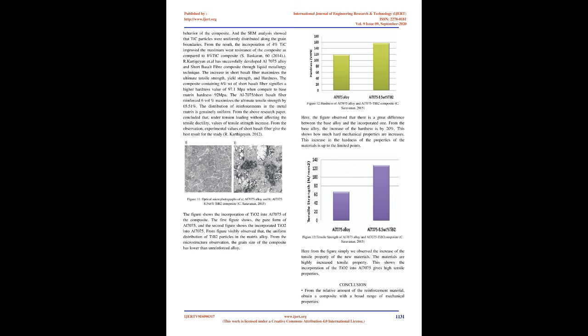Pradeep, 2014. Keshavamurthy et al. studied Al7075 TiB2, processed by stir casting technique using Al 10% Ti and Al 3% B master alloys. Matrix alloy and composite were subjected to microstructure analysis, micro-hardness test, grain size studies, and tensile test. Micro-hardness, yield strength, and ultimate tensile strength of Al7075 TiB2 composite were considerably higher when compared with unreinforced alloy. Figures 2, 3, and 4 show the composite materials of Al7075.